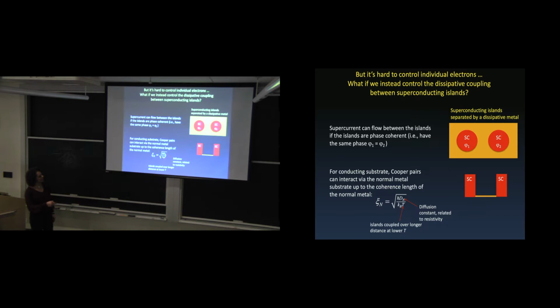So that means that if I have two superconducting islands and I lower the temperature to 0, for example, then these two should be coupled over even an infinite distance. Right? So as I lower the temperature, the distance over which the islands get coupled gets longer and longer and longer. And then I can couple these and see superconductivity between them.